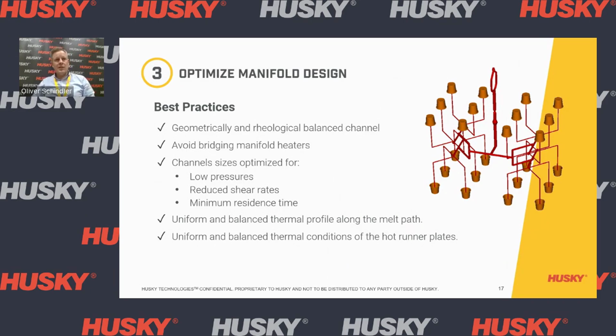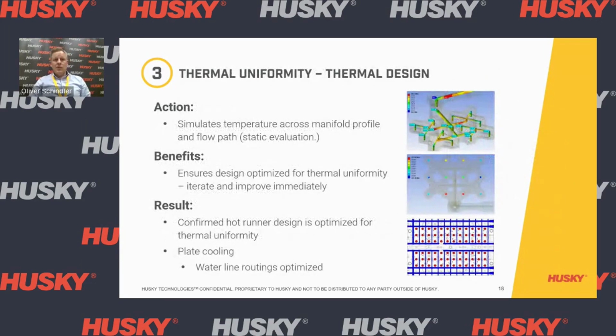And what you can see here is that low pressures and reduced shear rates require big channels, while the opposite, minimum residence time, requires small channels. And all our systems are running through a fill analysis prior to starting manufacturing steps to optimize all this in an optimum way, but I will show you a bit more about this later on. Thermal uniformity of a manifold design is also important.